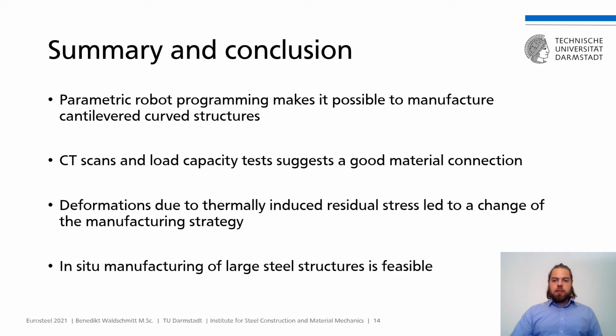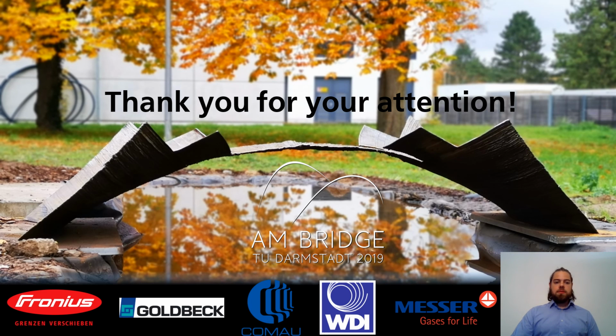To summarize our findings, the parametric robot programming in conjunction with the manufacturing strategy and process makes it possible to additively manufacture cantilevered curved structures. The listed process sequence characteristics ensure a stable manufacturing process. Spot welds in particular prove to be beneficial for this. The preliminary investigations on the fabricated scale bridge model, as well as the subsequent CT scans and load capacity tests, confirmed the assumption of a good material connection and sufficient load-bearing capacity. A change of the manufacturing strategy was required due to thermally induced residual stress, but it was shown that the in situ manufacturing of large steel constructions on site is feasible. Thank you for your attention.